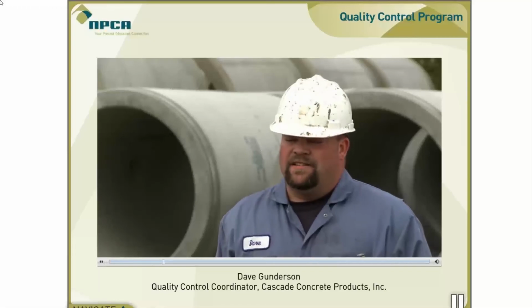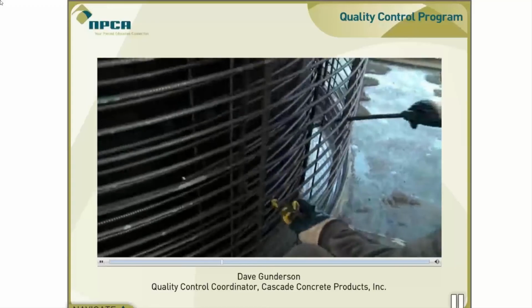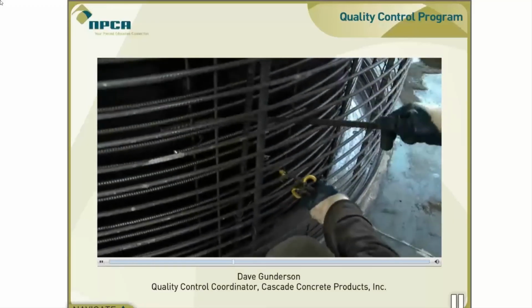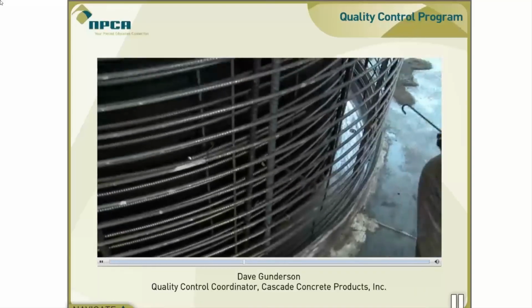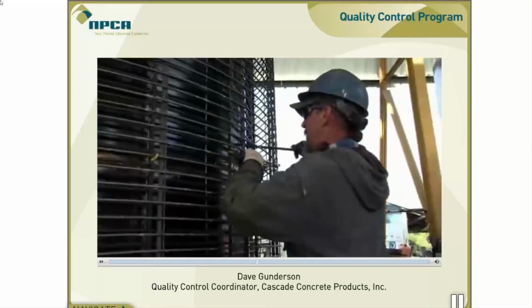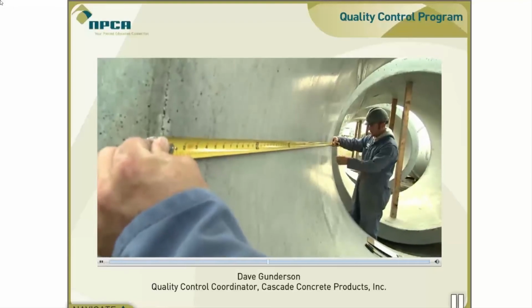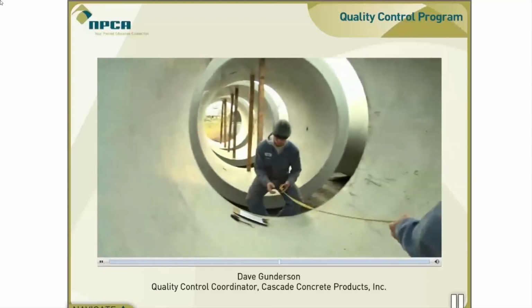It's pretty extensive. If you do it right, you have to, all the way down to the certification of the steel. You have to check the weights of the steel. There's testing to make sure that the aggregate is correct, sieve tests and water tests. And then we test the probes in the mixer to make sure they're calibrated correctly and that the right water cement ratio is going into the pipe. And then we check the steel clearances on everything before we pour the concrete, the clearances between the form and the steel, to make sure you don't get any corrosion, that water infiltration is not going to reach the steel. And then after the finished product is out, we check it again to make sure it's right again.